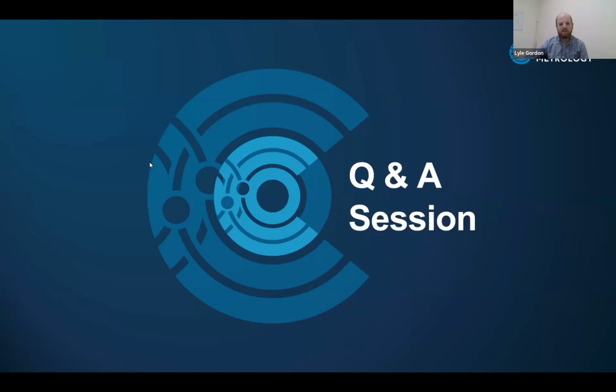Great, thanks. Another, I think, related question about sample limitations. If you have an uneven surface, or a rough surface, what sort of impact does that have on the analysis of your data? It's always better to have a mirror polished sample. In this case, you have excellent mass resolution, but obviously it's not real life. It will influence the intensity and the mass resolution, and the peaks will be wider, but there are some post-analysis methods to overcome this. We can work on the results and improve them, but then we know that the surface was very rough or even a little bit rough. Thank you.